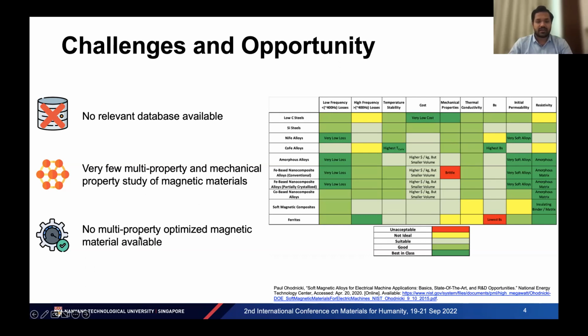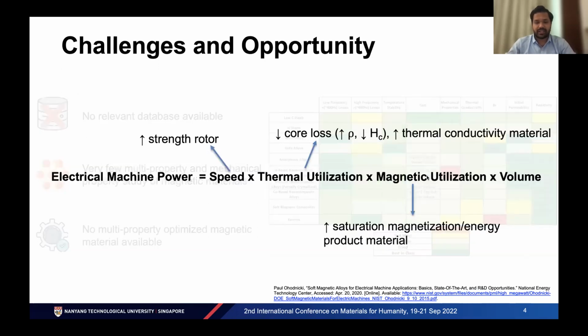Further, we found that there is no multi-property optimized magnetic material available, as can be seen in the table shown here. Some of the materials have very good magnetic properties, but they exhibit poor to moderate mechanical properties, and similarly poor to moderate electrical properties also. To solve such a highly complex problem, we think machine learning can help us.